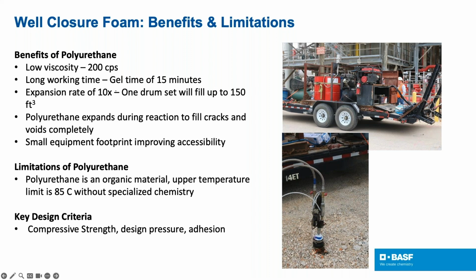Yeah, no problem. So as he was starting to say, the benefits of the polyurethane are listed here. So the materials have a low viscosity, which allows them to flow quite long distances. There's also a fairly long gel time. This can be adjusted, the gel time and viscosity, and most anything listed here can really be adjusted to your specific job. But the gel time of the system we have currently is about 15 minutes. So this also helps the material to flow, hundreds of feet, maybe even further. I mean, we've only tested, as Kyle mentioned, in the chemical pipelines that we had sealed.